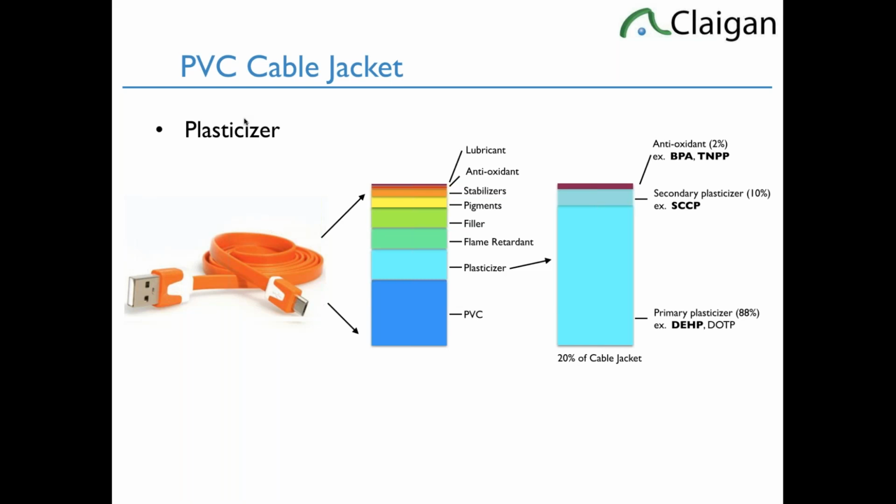It has something to do with the phenol group and why they're such good antioxidants, the antioxidants' job being to prevent the chemical from oxidizing or getting burnt by the oxygen in the air, by reacting or oxidizing or rusting in the air, which would create a color change and potentially a materials change. So when we get a BPA failure in PVC, it's normally coming through the plasticizer, which uses an antioxidant so that when the material is extruded or otherwise used, the plasticizer doesn't get oxidized.